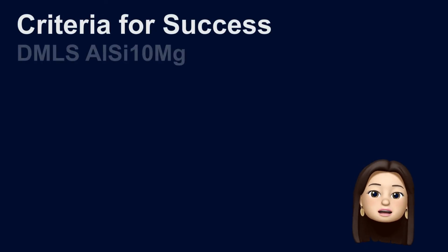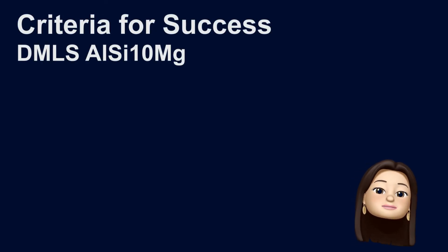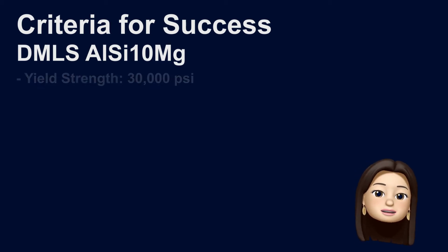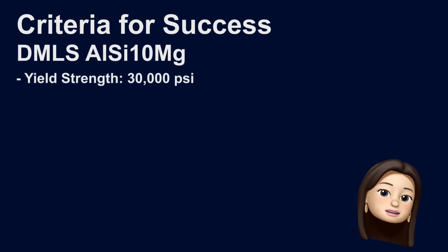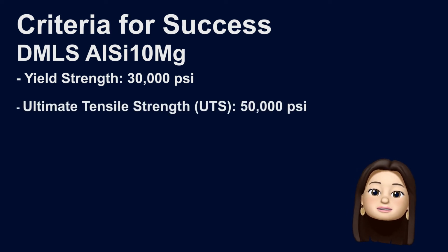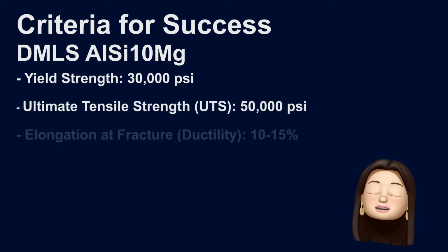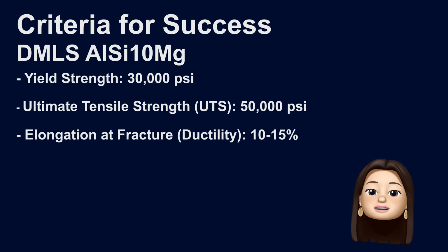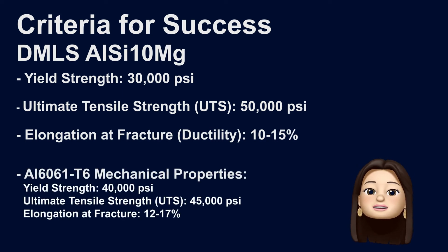The specific values that the team worked to achieve for DMLS aluminum silicon 10 magnesium were a yield strength of 30,000 psi, an ultimate tensile strength of 50,000 psi, and elongation at fracture of 10 to 15%. These mechanical properties were selected as they are very similar to those of the widely used aluminum 6061.